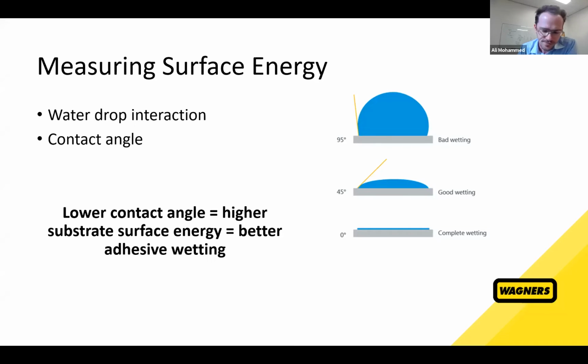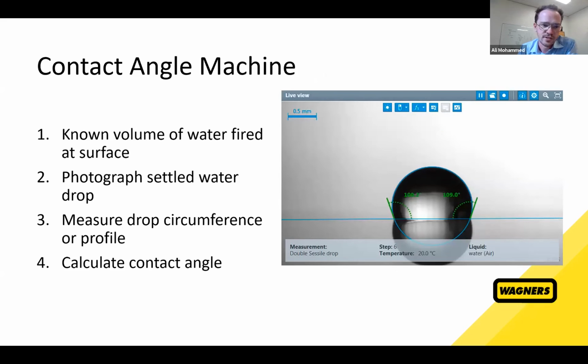So if you can somehow apply a drop of water to the surface and look at how the drop interacts, you can get a very consistent way of measuring the surface energy of that surface. Now, they've made machines that do this. A variety of different suppliers make machines that fire a drop of water at the surface and can tell you exactly what the contact angle of that water droplet to that surface is. You can then use that to consistently determine the surface energy of your surface. It fires a known volume of water at the surface, and then photographs the drop sitting on the surface. Then, either from a side profile or top view, it calculates the contact angle of that water drop.